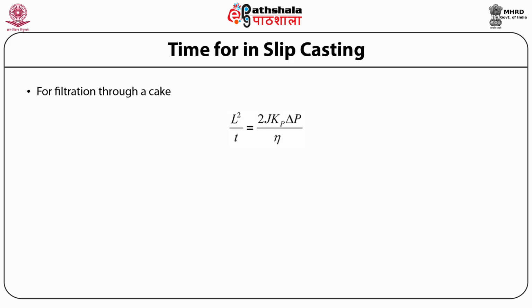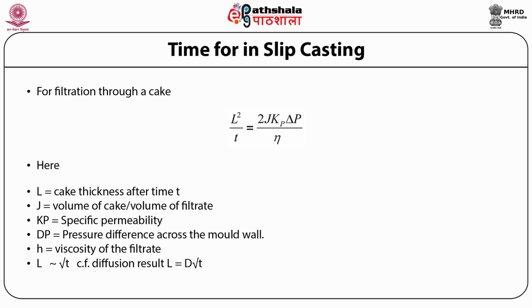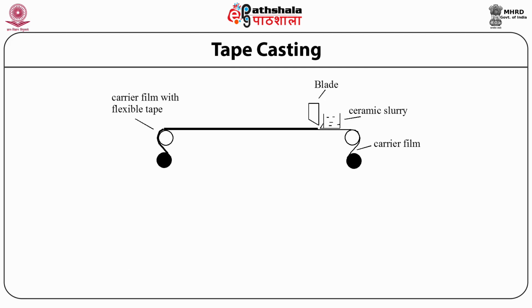For the filtration through a cake, one gets the formula L squared by T is equal to 2J Kp delta P divided by eta, where L is the thickness of the cake produced in time T, and J is the volume of the cake per unit volume of the filtrate. This equation shows that the thickness of the cake increases as the square root of the time of casting, and it is similar to the diffusion equation, which is L is equal to D times root T, where L is the thickness through which the diffusion of the species takes place in time T and D is the diffusion coefficient. Now the next process is tape casting.